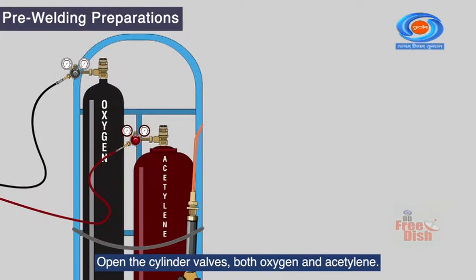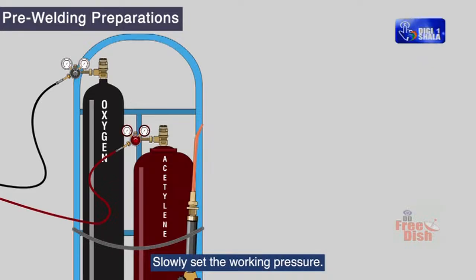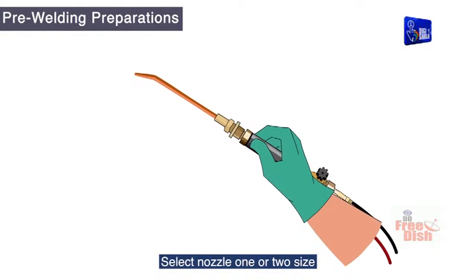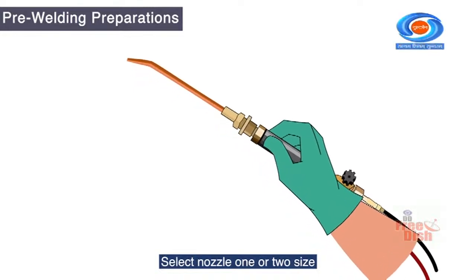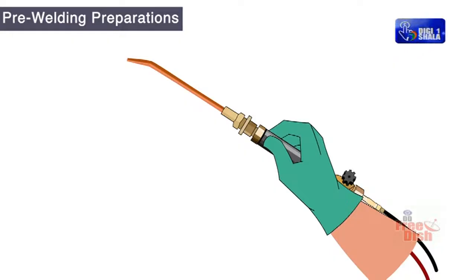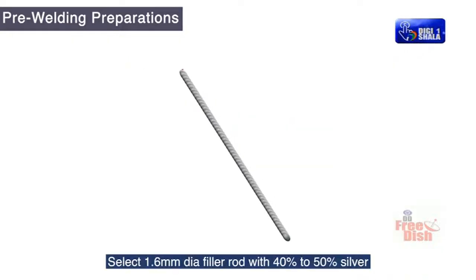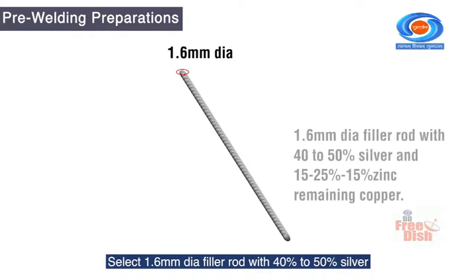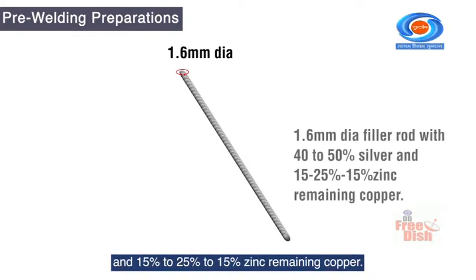Open the cylinder valves, both oxygen and acetylene, slowly. Set the working pressure. Select nozzle, 1 or 2 size bigger than the sheet thickness. Select 1.6 mm dia filler rod with 40 to 50% silver and 15 to 25% zinc, remaining copper.